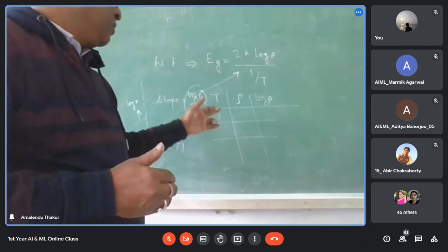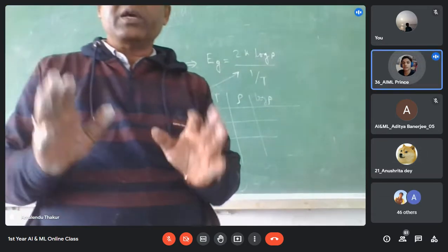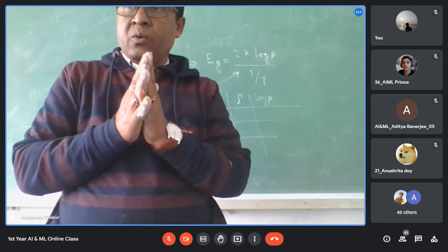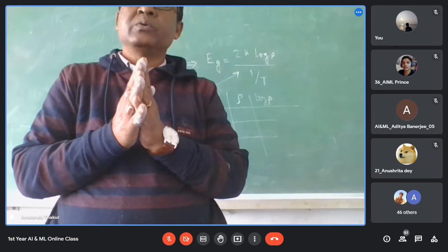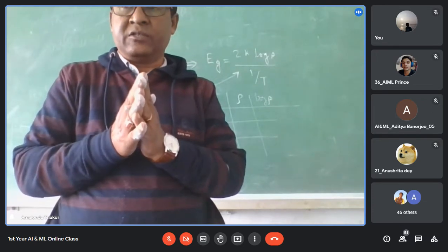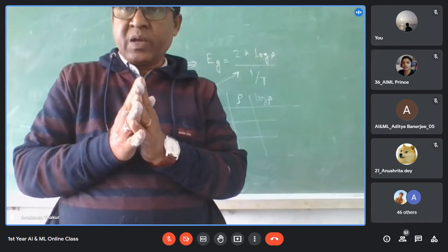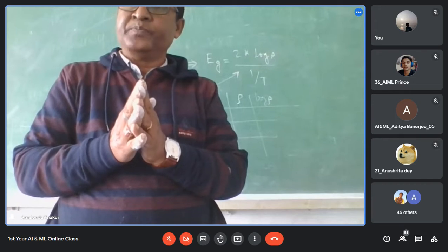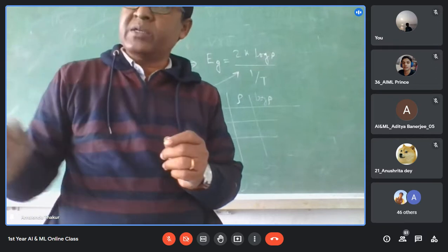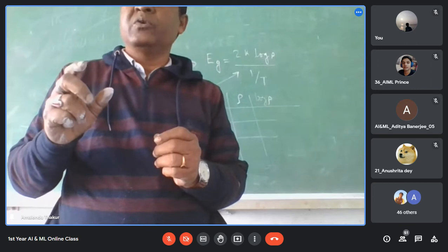How many readings? That is 10 to 15. One thing, students, just listen to me. We have to increase up to minimum 160 degrees Celsius or 200 degrees Celsius. In between, you may take several points at your choice. If you take many points, then it will be easier to draw the curve.